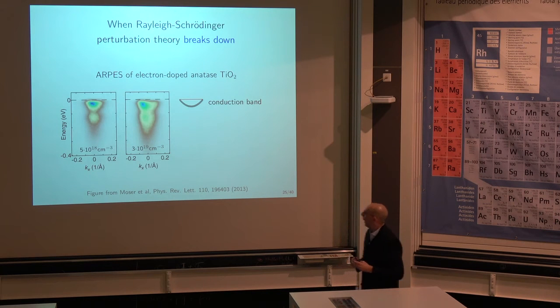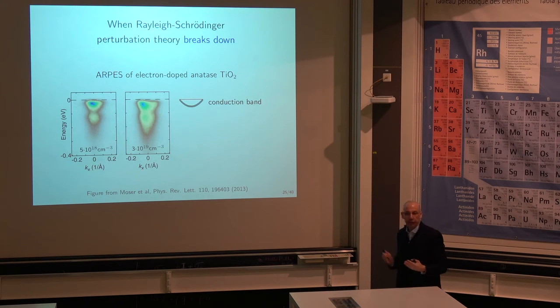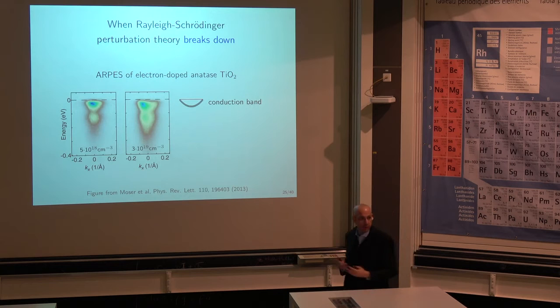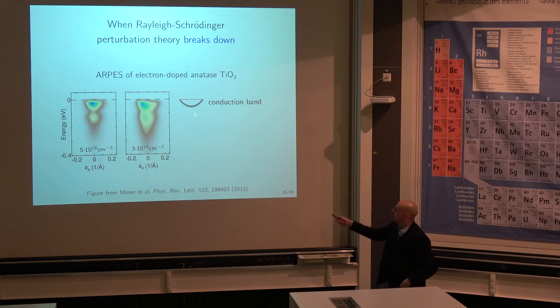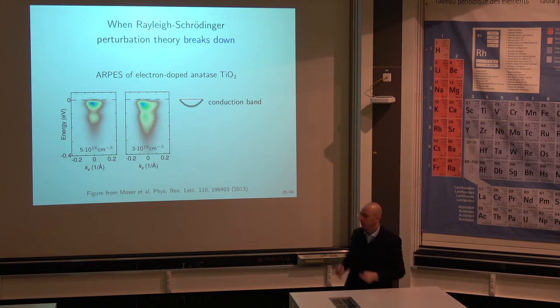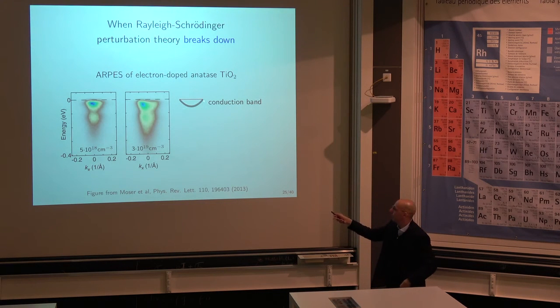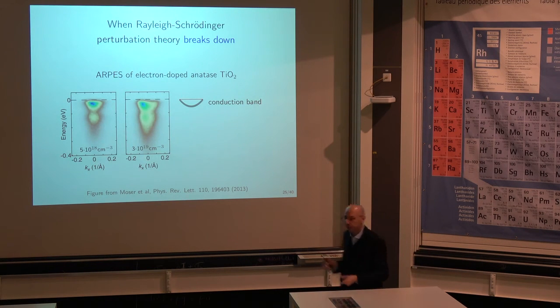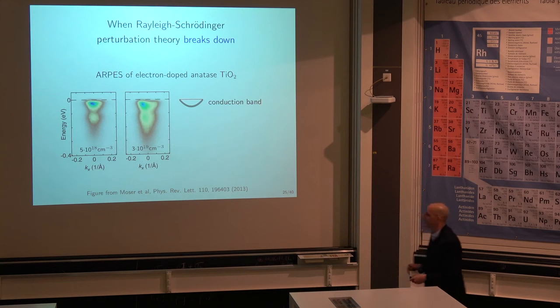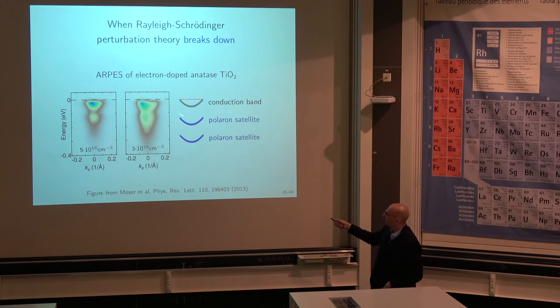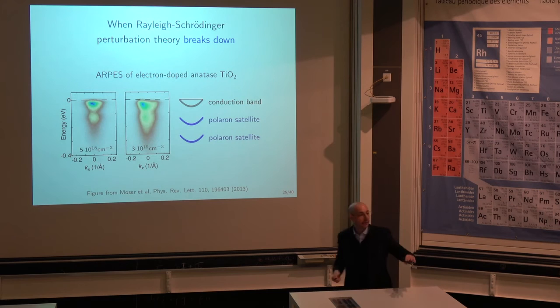So if you do a band structure calculation and you use the doping levels that they were considering in the experiments, you would obtain something like this, a little parabola, because you're doping a conduction band minimum, right? In the experiments, they don't see a little parabola like that. They see this, then there is some stuff here. If you analyze the experiments carefully and extract information, you will see that there is a band here, then there is some kind of replica, and then another replica, and they are smaller and smaller in intensity.